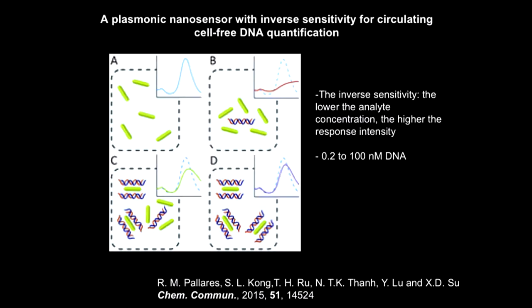One of the applications we use with the gold nanorod is sensing. We can sense many different things, but I'll just give you the principle. When we make a gold nanorod, it is positively charged because we make it with the molecule CTAB. And DNA, as you know, with the phosphate backbone, is negatively charged. So when you put the negative to positive, you neutralize, there is no repulsion, and then it's going to aggregate. That's what you see, that they aggregate, and you can see the long absorption at the longer wavelength, the same as what you see in the spectrum I showed you before with the gold nanoparticle.